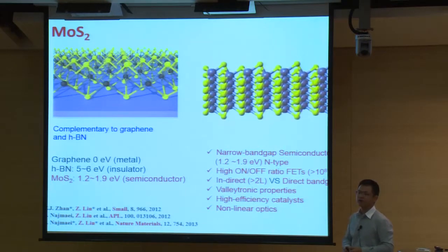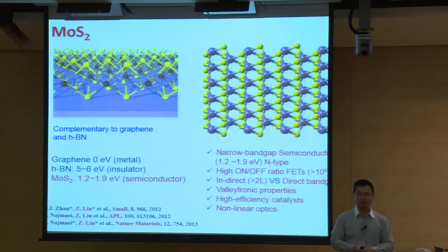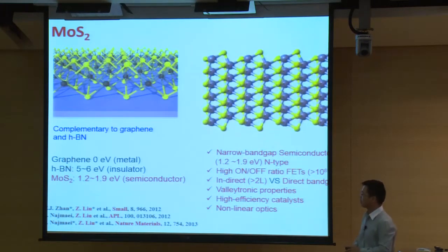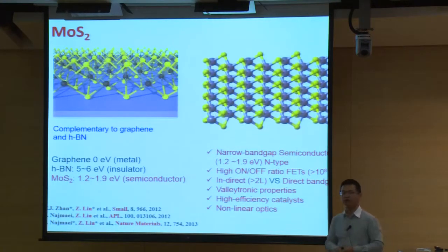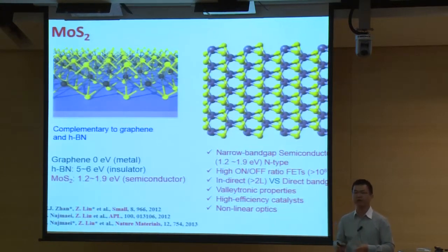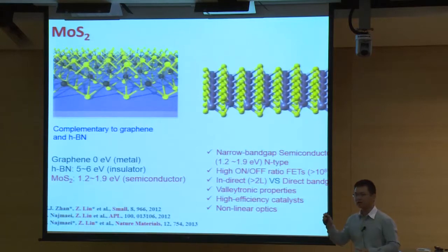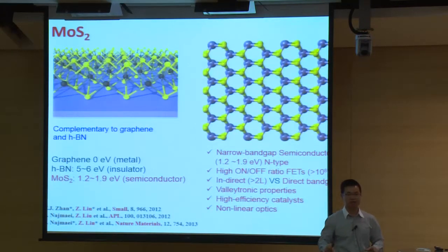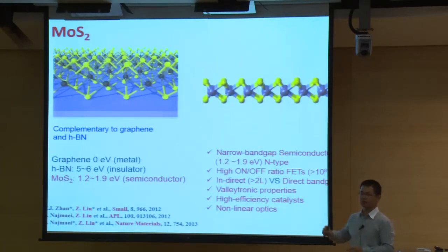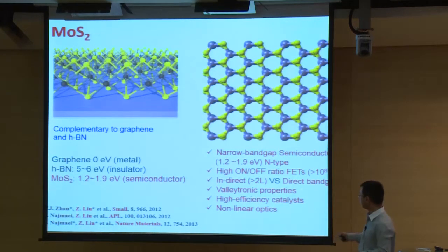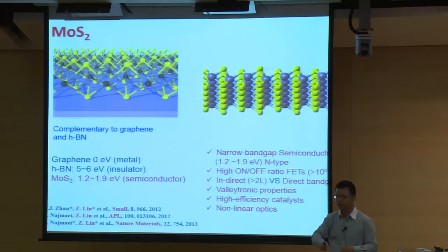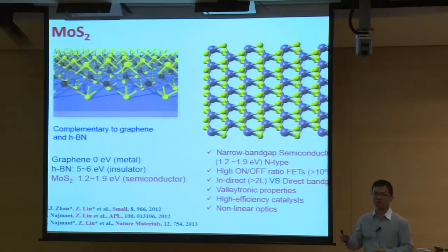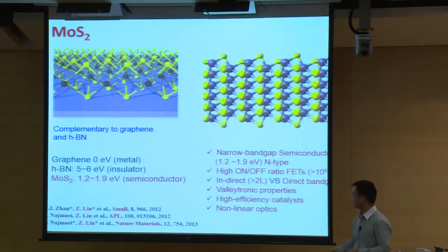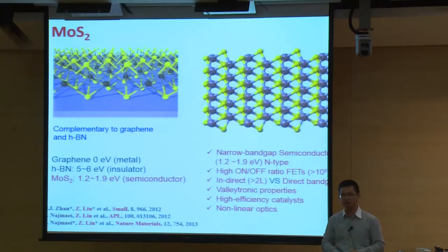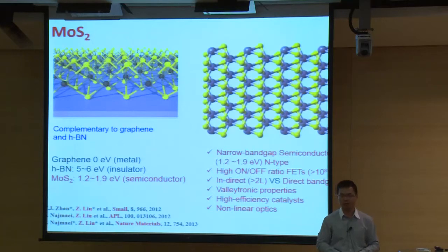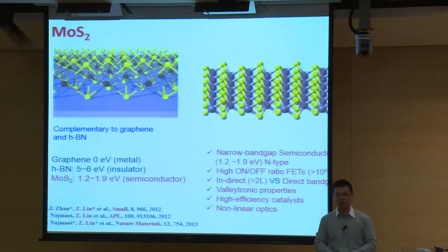Okay, molybdenum sulfide is a very typical member of this big family, and it has been commercially used as a lubricant. But the reason we like it now is because we have a highly electrically conductive graphene, and we have insulating boron nitride. So molybdenum sulfide is the last piece we're looking for as a narrow bandgap material. And because of this narrow bandgap, the on-off ratio of molybdenum sulfide can be as high as 10^8. And also, if we make molybdenum sulfide from the bulk to a thin layer, we can see the transition from indirect bandgap to direct bandgap, which results in the valleytronic properties of these materials. And also Noah mentioned the catalytic and nonlinear optical properties. I think all of these properties have been discussed in the previous 2 days.